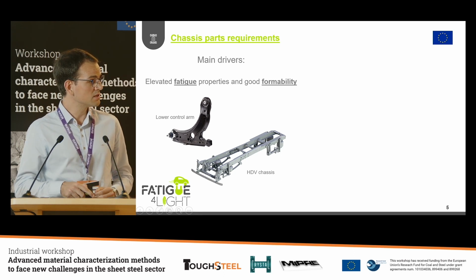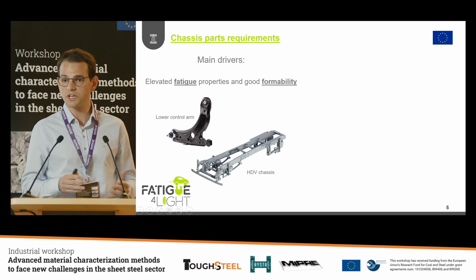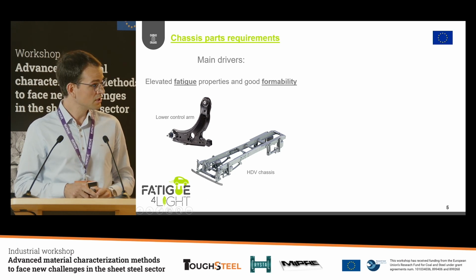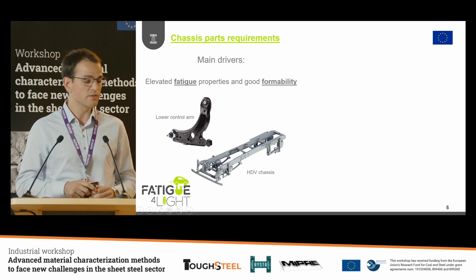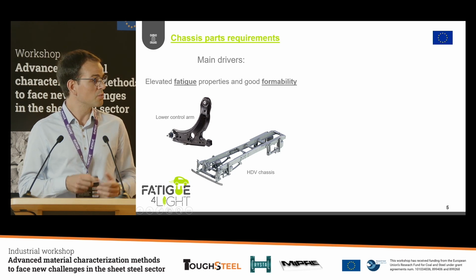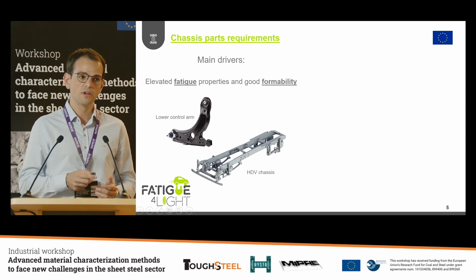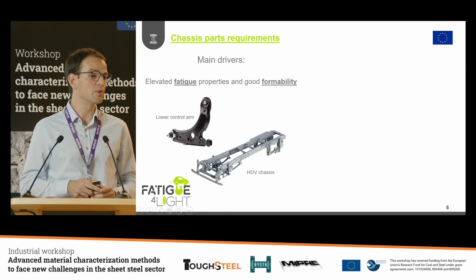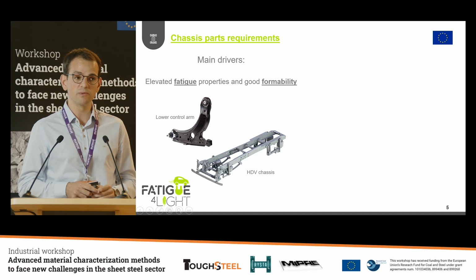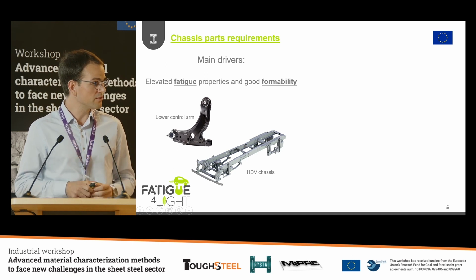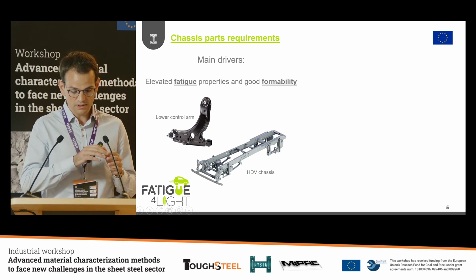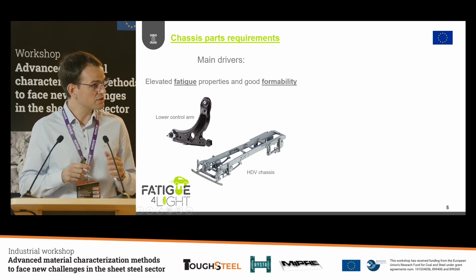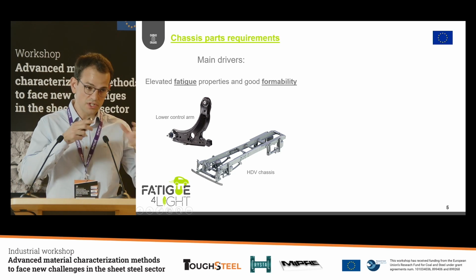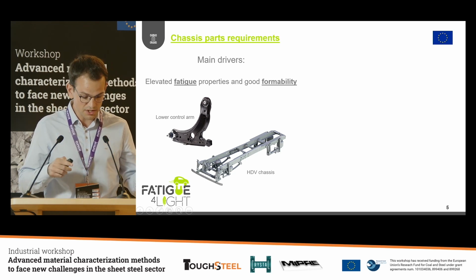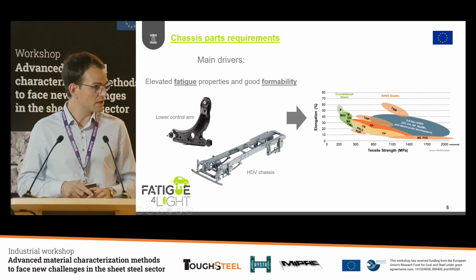So in this case, here you can see two different chassis components, a lower control arm, and also the chassis of the heavy-duty vehicle. And if we want to reduce the weight of these components, we need materials with good fatigue properties, but also with a good formability. Since we are decreasing the thickness of the material, we have to maintain the stiffness of the component. So this stiffness reduction can be compensated by changing the shape or slightly changing the shape of the component. So we need a good formability.